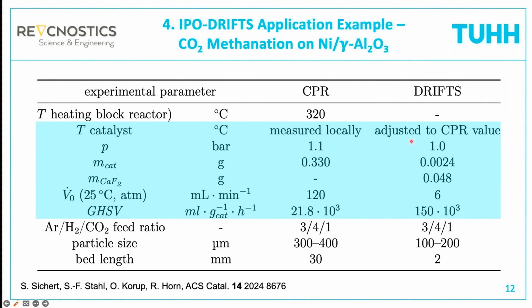And now I want to give you some numbers to illustrate how this isopotential experiment works. So in our reactor, we set the heating block of the catalyst to 320 degrees. But the real catalyst temperature we measure locally with our spatial profiling technique. And then we adjust in the DRIFT cell the temperature value to what we measure locally in the reactor. In terms of pressure, we have 1.1 bar in the CPR and 1.0 bar in the DRIFT cell. So you see we have only a pressure drop of 100 millibar. It's almost the same pressure as in the reactor.